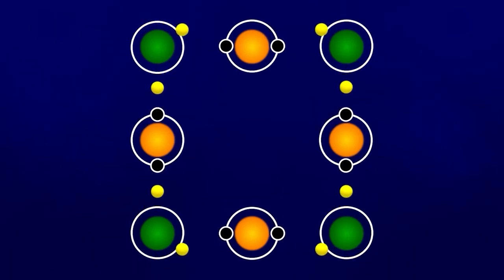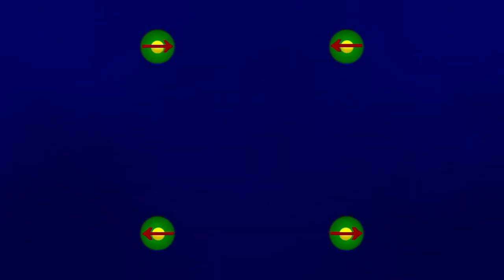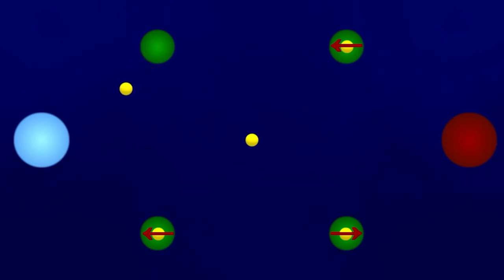Copper oxide forms due to the sharing of valence electrons from copper atoms, which occupy the vacant orbitals on the 2p sublevel of oxygen atoms. Since electrons are fermions, each orbital can accommodate a maximum of two electrons, with opposite spins. As a result, the spins and magnetic moments of valence electrons in neighboring copper atoms must be oriented in opposite directions. This orientation is termed antiferromagnetic. In such a structure, there are no free charge carriers, and it seems that there isn't a basis for Cooper pairs to form. However, this is where we need to recall that our material also contains barium and yttrium atoms situated above and below the copper layer. These atoms can play a role similar to impurity atoms in semiconductors. They can break the symmetry of the main layer, either by adding electrons to it, making them donors, or by taking electrons from it, making them acceptors.